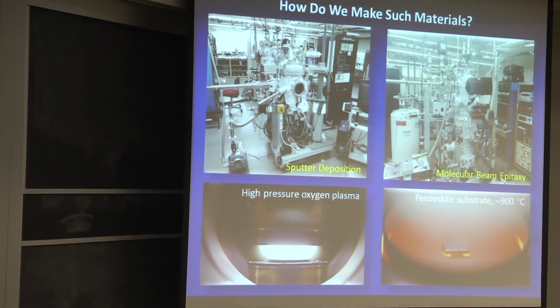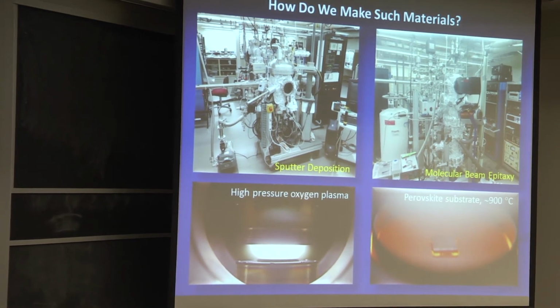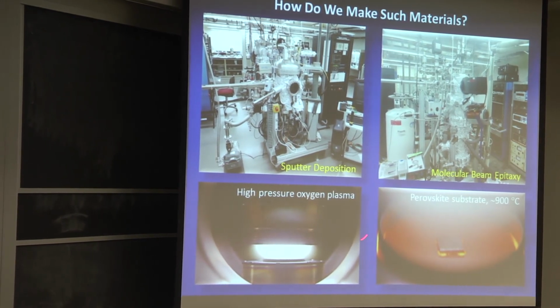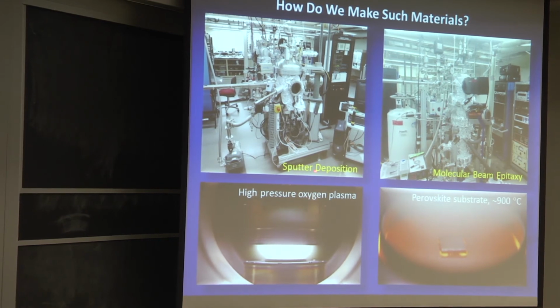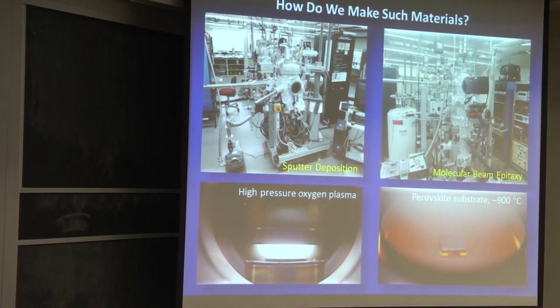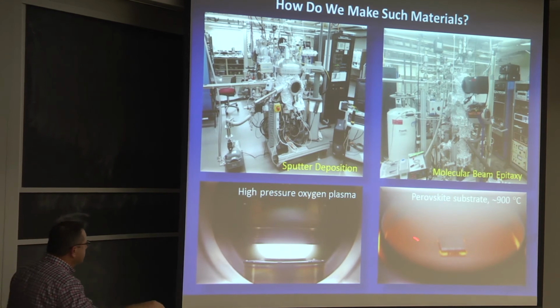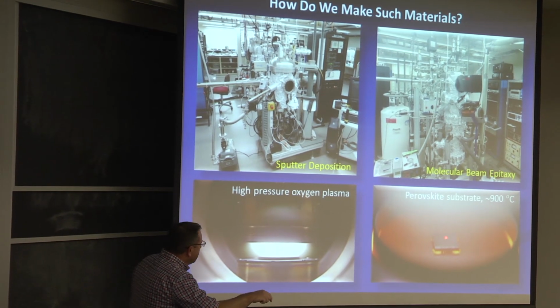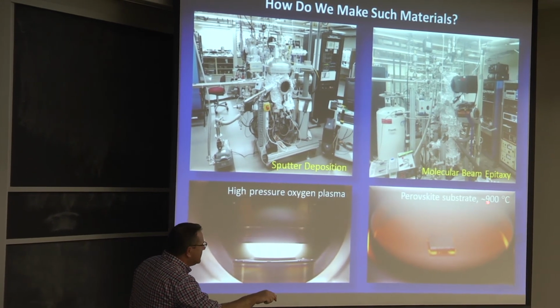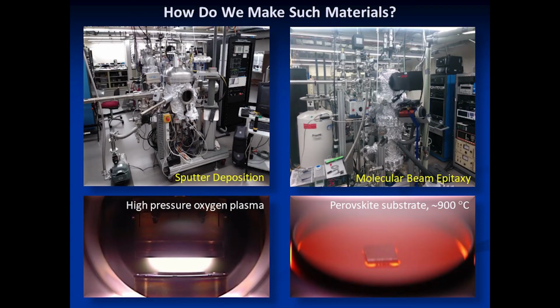So this is how we make this stuff. If you're ever down in my lab, and you're welcome to come and have a look, you'll see these big chunks of stainless steel. They're used to do things like sputtering and molecular beam epitaxy. This is one of those processes running. This is a perovskite substrate. It's been heated up to 900 degrees C. These things crystallize at pretty high temperatures, and we're literally raining down atoms from a plasma in a sputtering process on the surface of that thing. And if we get all of the conditions exactly right, then we will grow the perovskite structure that we want, the ABO3, and we can do some experiments, right?